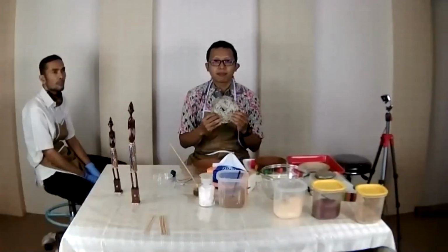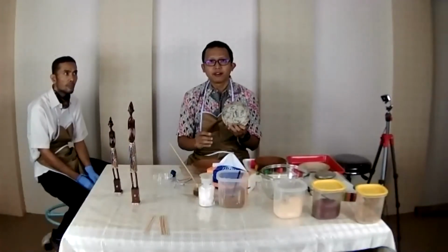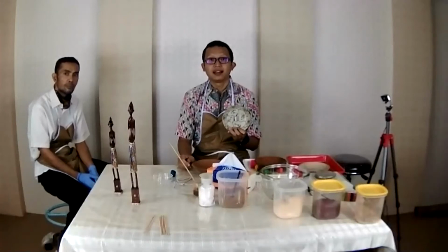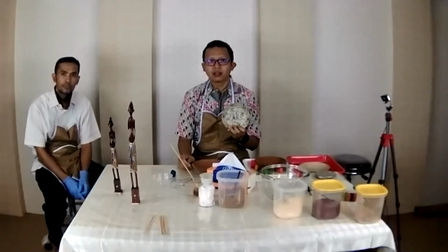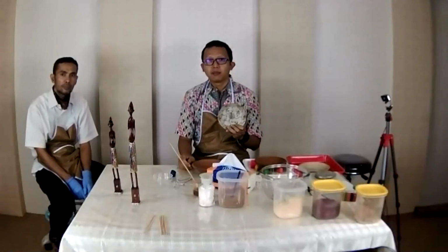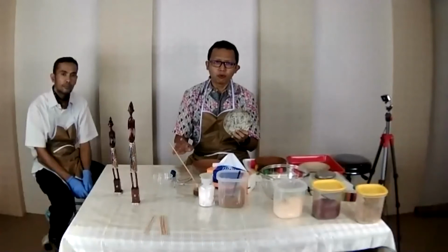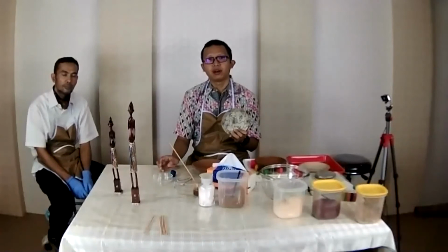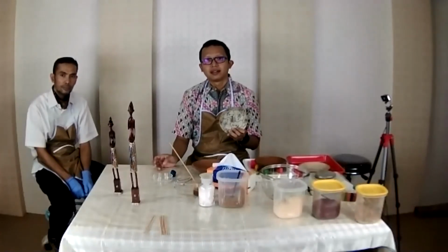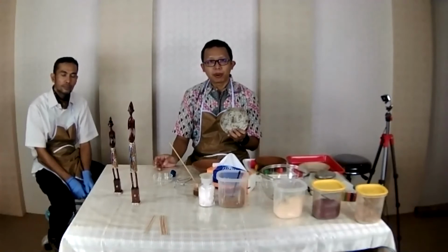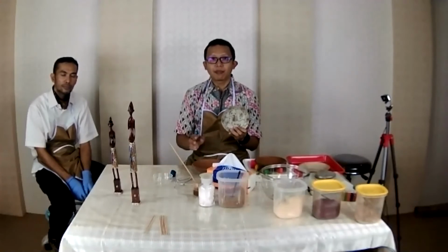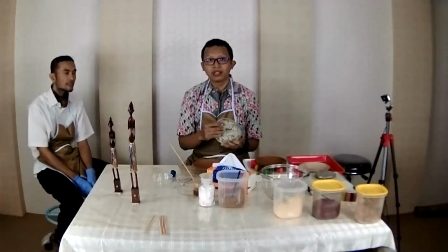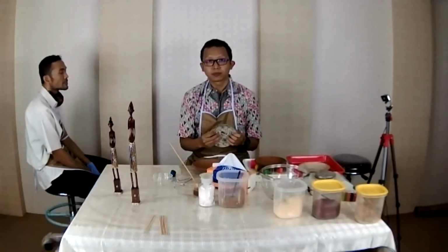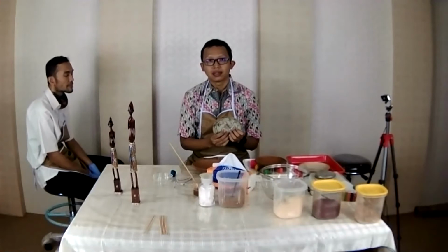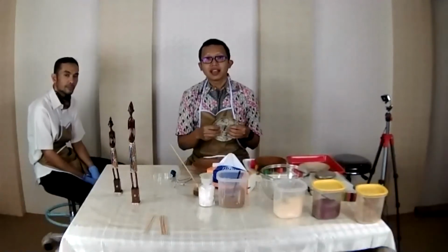The ceramic that we repaired, we store in a room with a very controlled condition, very small fluctuation. The humidity is about 40 to 60%. So we keep the room in controlled condition. We have no other treatment applied. So it's naturally like that.